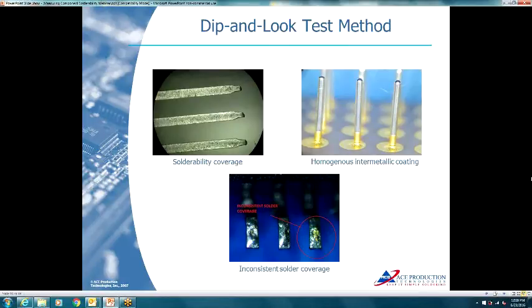Here are some examples after a dip and look test. The image in the upper left shows solderable coverage that's greater than 95%. The image at the bottom shows inconsistent solder coverage, very bad wettability. You can see gaps and inconsistencies. That's probably, again, bad terminations, a lot of oxides, and sitting on the shelf for a long time. In the upper right-hand image, you can see a component that was retinned, with a homogeneous intermetallic coating, and what a good coating would look like. That's closer to 100% than 95%.